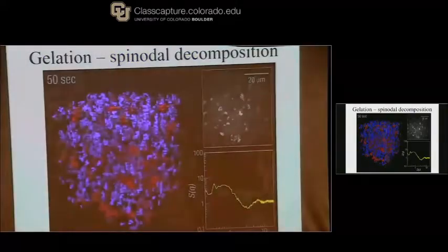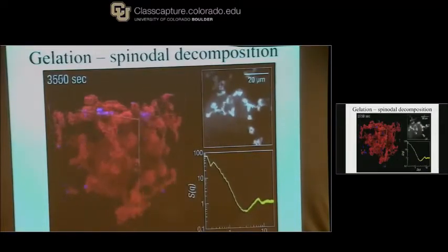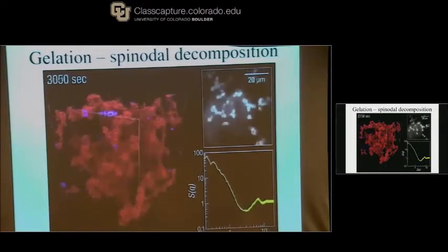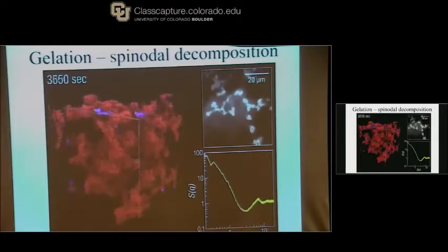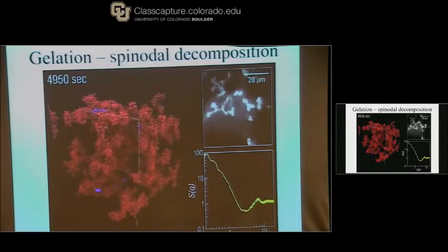So what's happening is, as you start, it's undergoing spinodal decomposition. But then it gels. So why does it gel? The reason it gels is that the clusters here are attractive enough, are solid enough, that they're jammed, forming essentially a solid structure. They're forming, if you want, an attractive glass or jammed system.